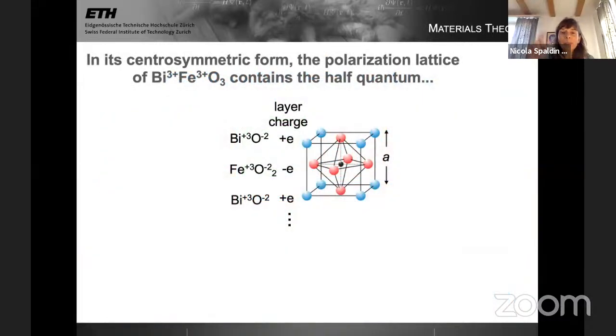Okay, but to find happiness, there's another aspect of bismuth ferrite that we need to understand. And that comes back to this weirdness of centrosymmetric materials having polarization lattices that don't contain 0. And bismuth ferrite is actually an example of one of these. In its centrosymmetric structure, in its high symmetry perovskite structure, where the bismuth ions are not displaced, this is the structure of bismuth ferrite at very high temperature, the so-called paraelectric structure, the polarization lattice contains the half quantum.